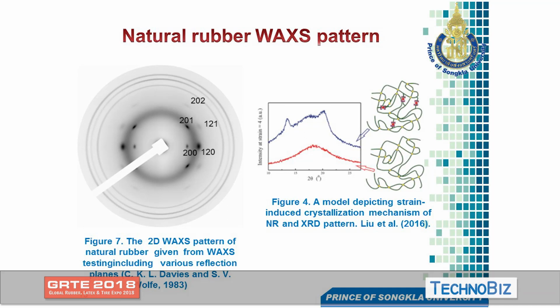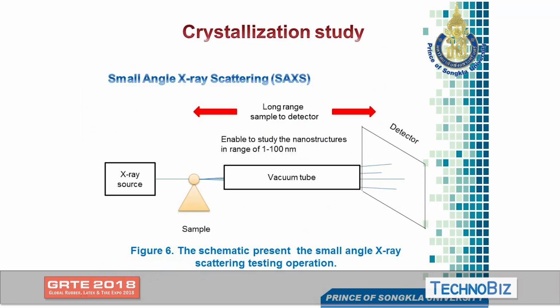This is the previous image that I've shown you before. If there is strain-induced crystallization, two additional peaks appear. This is the amorphous part, and this is the crystalline region that appears after being stretched. This is a 2D image from the wide-angle technique. Because I study strain-induced crystallization, the sample must be stretched, and then we monitor the crystal peaks simultaneously.